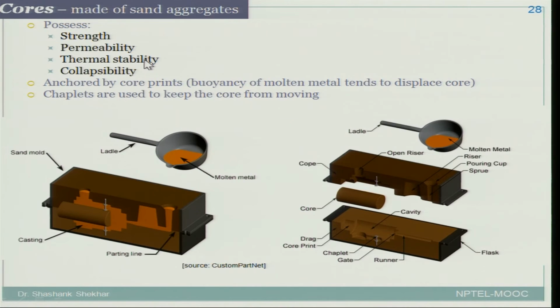Another is thermal stability, because we are talking about liquid metal temperature which is of the order of 1200 or 1500. So the core must be able to retain strength even at those temperatures. So thermal stability must be there.